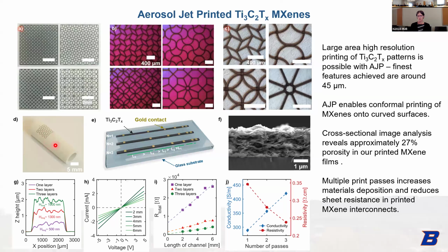Here's an example where we printed on an aluminum tube. This is a 5mm bar, so about a 10mm diameter. So we can print the pattern directly on a 3D surface. We did do some TLM measurements and show that as we increase the pass number, print pass, and then we go over it again, 2 and 3, we increase the thickness of the MXene layer and reduce the resistance.